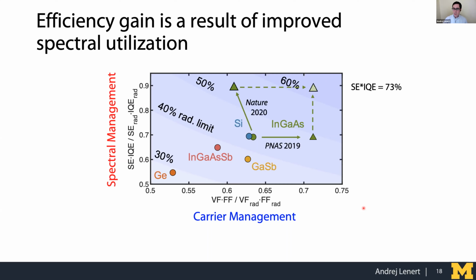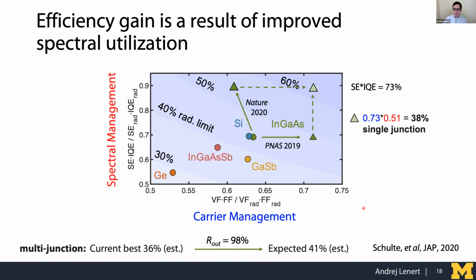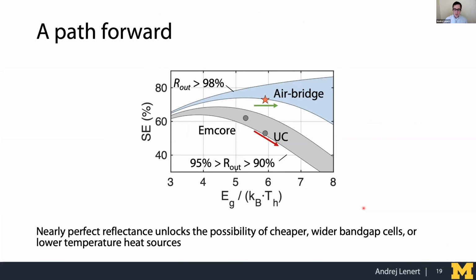And so if we were to come up with a hypothetical scenario that does this, I would expect that in the very near term, we would see single junction efficiencies at 1500 Kelvin for InGaAs that are approaching 40%, about 38%. And I also want to acknowledge that this is single junction efficiency. Efficiencies can be higher for multi-junctions. And there's work out of NREL and MIT that has shown about 36% absorption efficiency with a multi-junction cell. And using their models, they estimate that if the reflectance goes to 98%, they can exceed 40% efficiency.